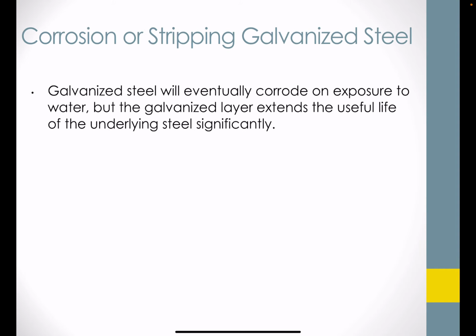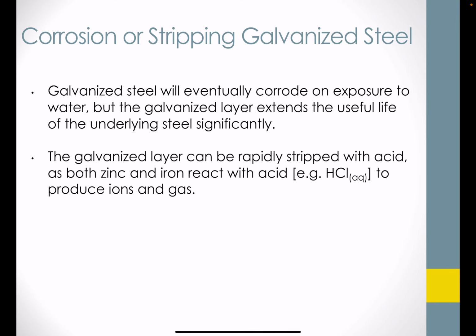Okay, so in order to reverse engineer and understand a galvanized coating on steel, we'll need to understand the corrosion and stripping chemistry of the galvanized steel samples. So galvanized steel will eventually corrode, as you might expect, and this will occur under exposure to water, but the galvanized layer will extend the useful life of that underlying steel because of its electrochemical action on that metal structure. So the galvanized layer, for us in this lab, we'll see can be rapidly stripped with acid. Okay, so this is to say that we recognize that zinc solid can be digested away using HCl.